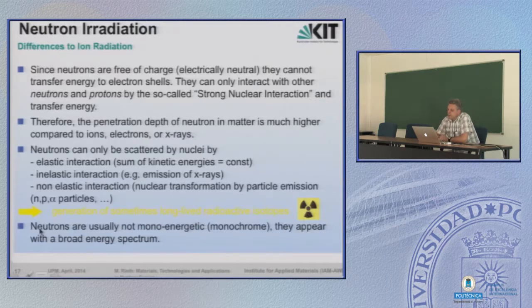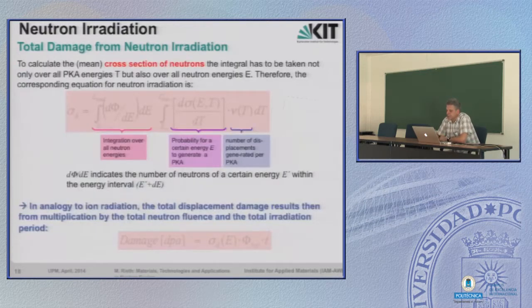And another important difference to ion irradiation is that neutrons are not mono-energetic like the ions. Ions are produced by acceleration. So if you have an accelerator with, for example, 50 keV, all ions have the same energy. That's mono-energetic ions. But neutrons, you cannot do this. Neutrons have, therefore, a broad energy spectrum. They appear in a variety of different energies. So this is the difference.